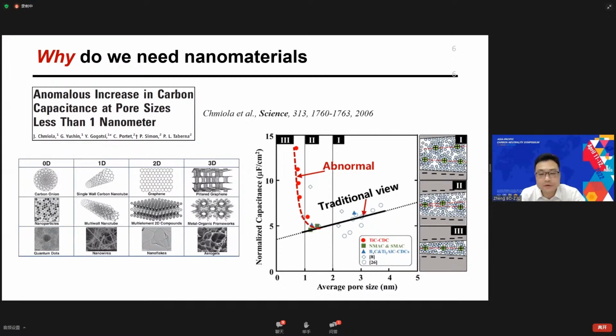This was first demonstrated in 2006. As you can see here, it was published in the Journal of Science, and it reports that capacitance could be largely increased at pore sizes less than 1 nanometer. However, at the same time, it shows quite unique electrostatic adsorption features compared to activated carbon.